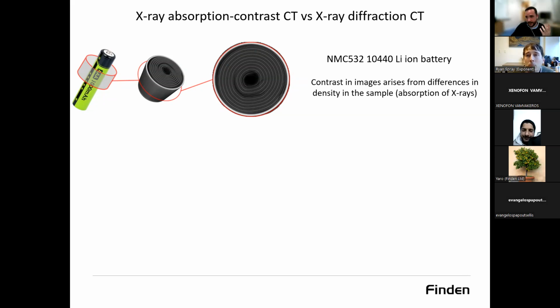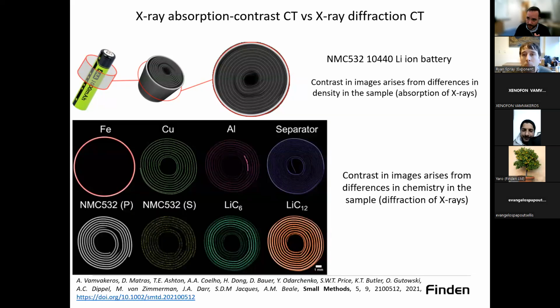So, X-ray diffraction computed tomography. We look at the diffracted signal, and this is most often performed at synchrotron facilities. We are able to get back this lost information because the contrast arises from differences in the chemistry of the sample, from the diffracted X-rays.